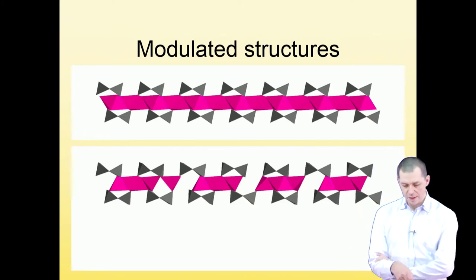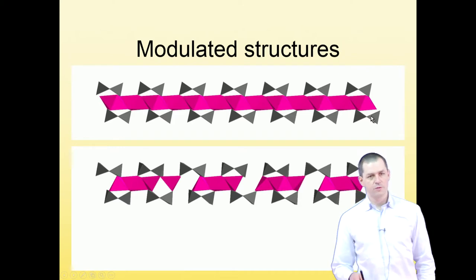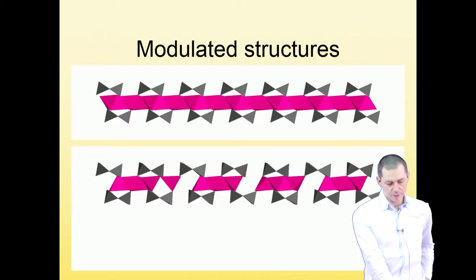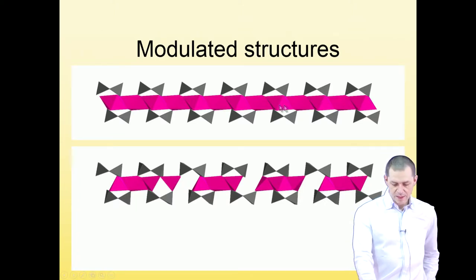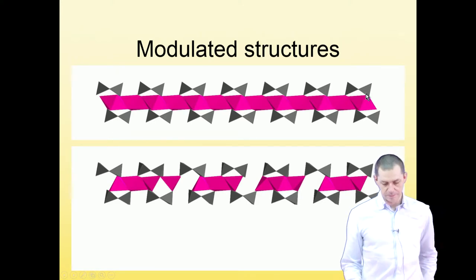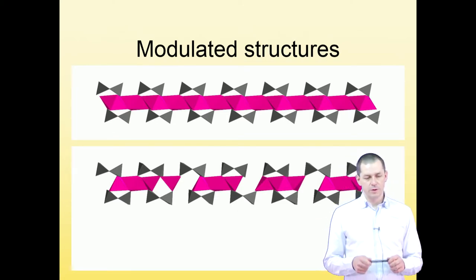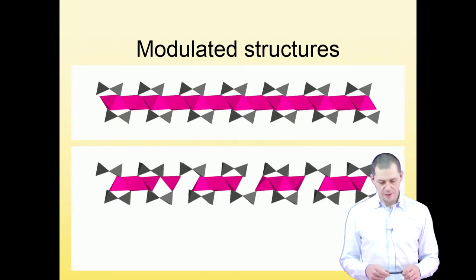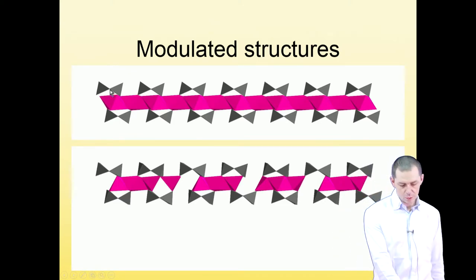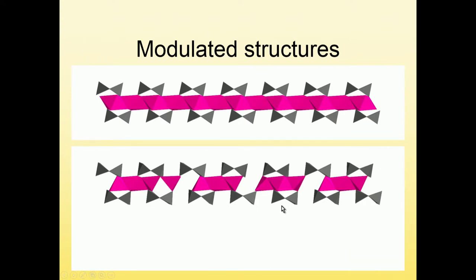This is a structure of chromium diphosphate. And here in the upper part, you see the structure of that material at high temperature. And you see that it is a periodic arrangement of chromium octahedra and P2O7 diphosphate groups that are bridging them. If you cool that material down, the structure changes to an incommensurately modulated structure, and it looks like this. Now you see that the P2O7 groups are not periodic anymore. There are slight changes in the positions of the bridging oxygen. So here it's down, it's higher, it's quite up, very much up, and here it's down again. So there are shifts. And moreover, the coordination of chromium changes. It's not octahedral coordination anymore, but it's an alternation of octahedral coordination and square pyramid. And there is a gap, and then again, pyramid, octahedron, pyramid, gap.